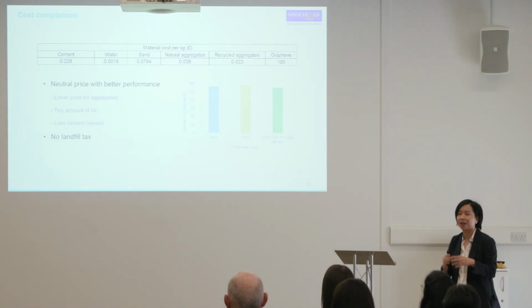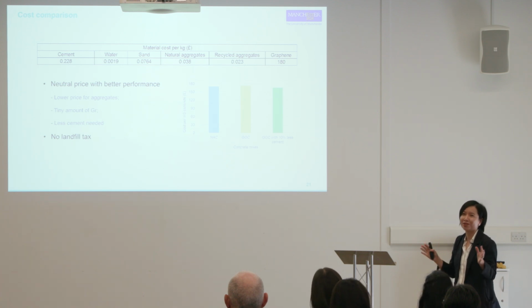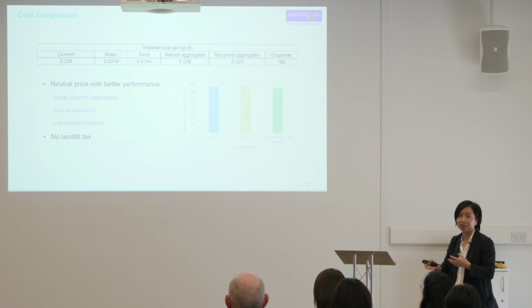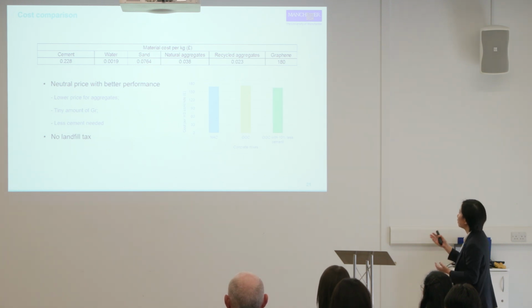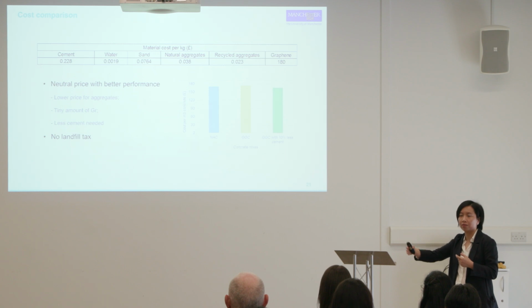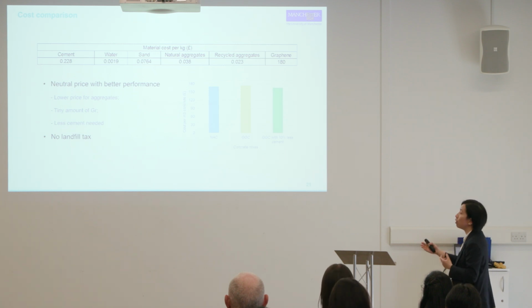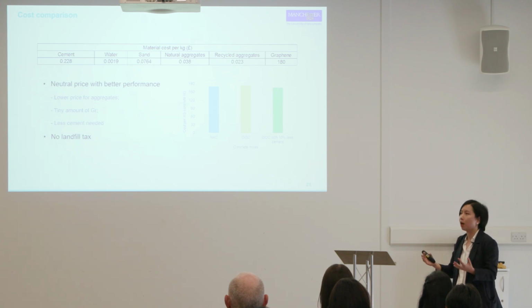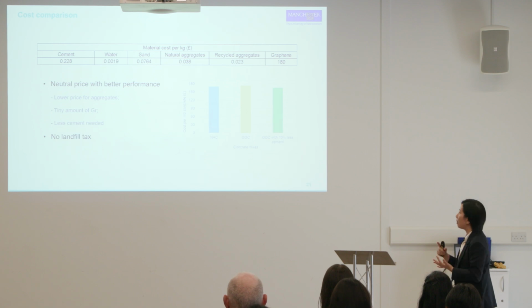And we also did the cost comparison for those mixtures because we know price and profit are very sensitive in the concrete industry. So any change to the price can make a significant change to the adoption of the new product. Through the cost comparison analysis, we found that the graphene green concrete has a competitive price to the conventional commercial concrete. Even though we know that the price for graphene is still relatively high, in this mixture we use a tiny amount of graphene. Also because we use recycled aggregates, and the price for recycled aggregates is lower than natural aggregates, we managed to keep the price neutral. And in addition, if we consider the landfill tax saved, the price for graphene green concrete can be even lower.